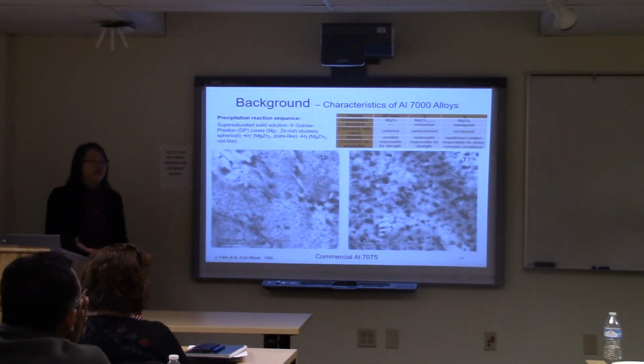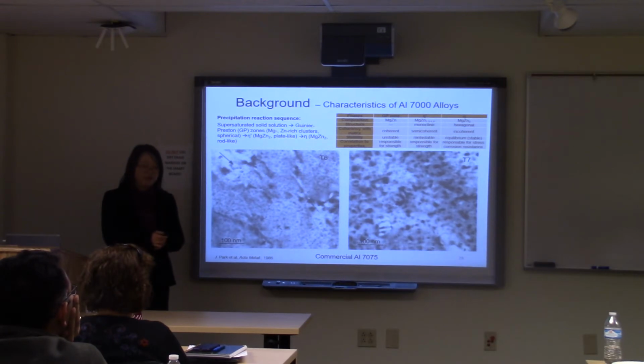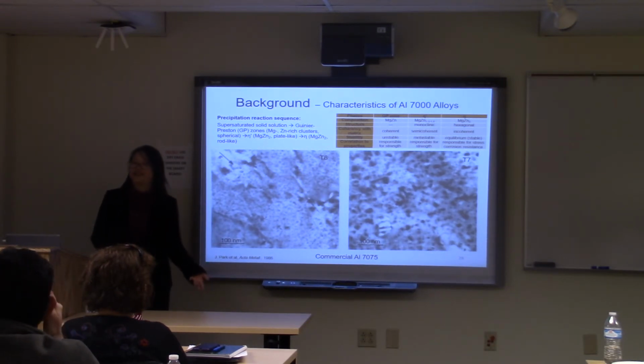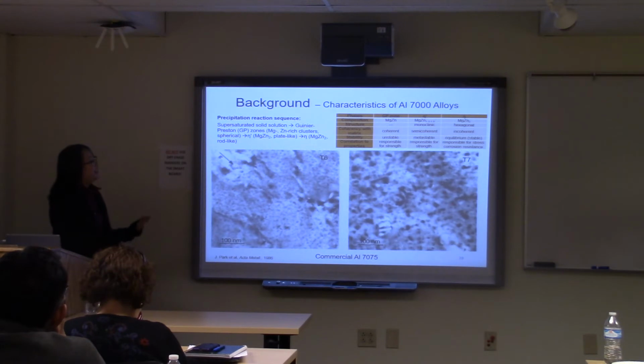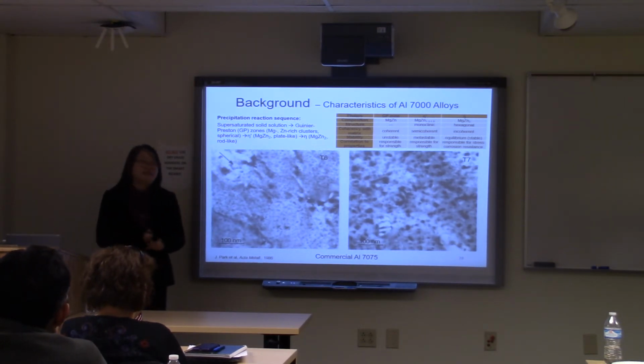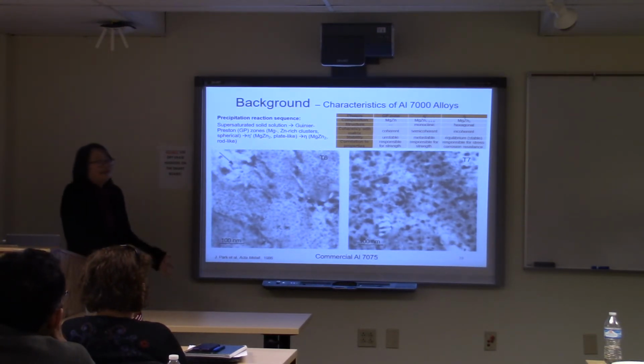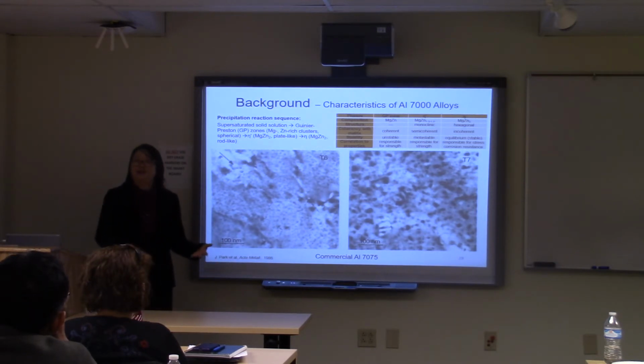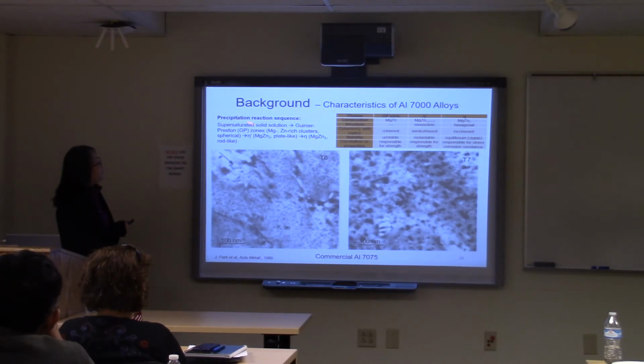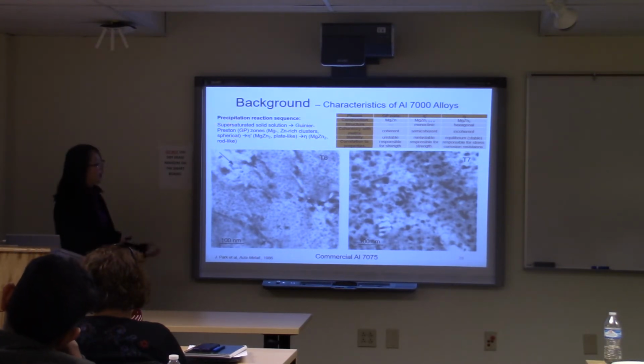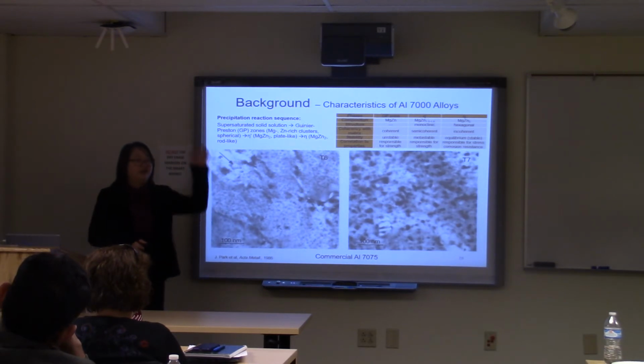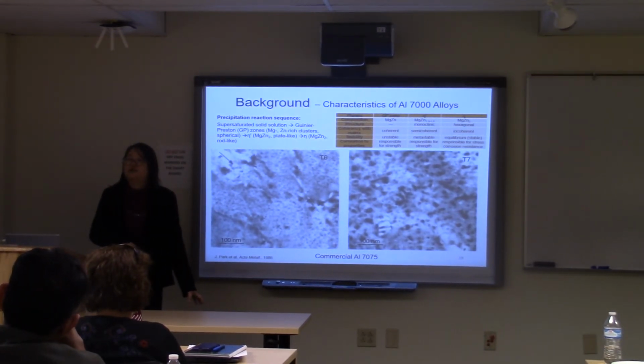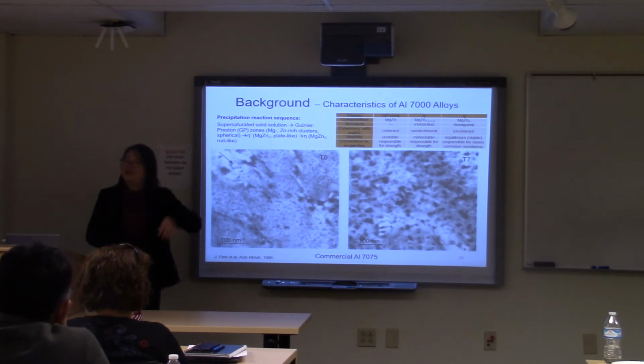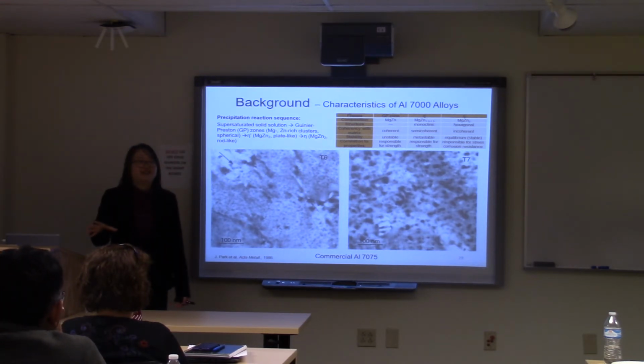So what contributes to this special hardening response to the heat treatment? It's time again to look at the microstructure inside this alloy. Reminding you, this alloy contains magnesium, zinc, and copper in it. Those elements are not perfectly 100% in solid solution in aluminum alloys. So usually you will heat the material up to a high temperature and then quench it down at a very fast cooling rate. If you look at the phase diagram, that's the method where you can put more solutes in the matrix than the equilibrium state.